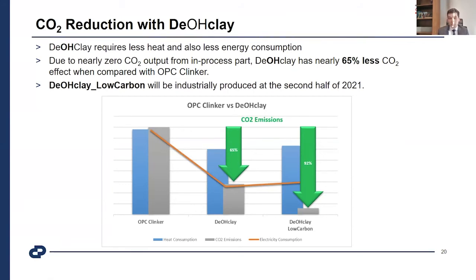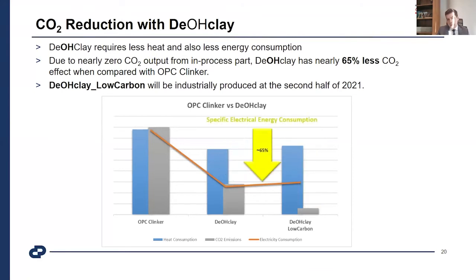It's just related to dehydroxylation, where hydroxyls, water vapor, are removed, and it helps to decrease emissions if the heat energy can be supplied from lower CO2 emission materials and fuels. Then there's a chance of more than 90% decrease. And specific electricity consumption, when compared to OPC clinker, is nearly 65% less required while producing DeOHclay.